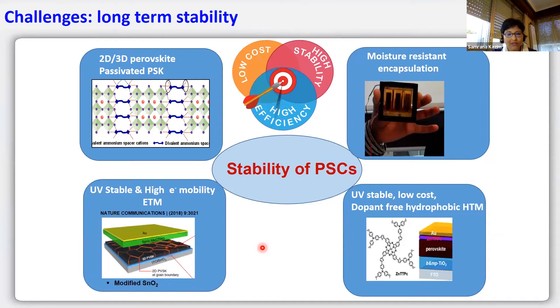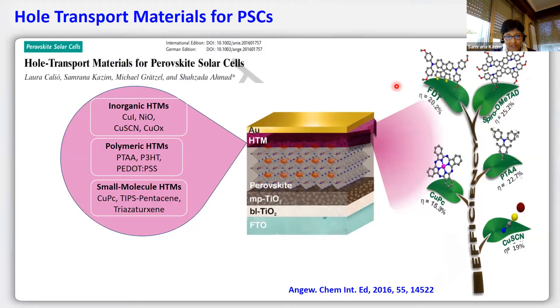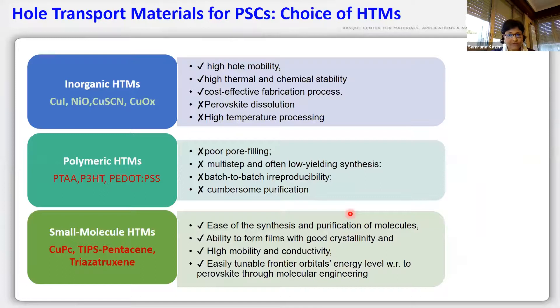We have been working in this direction since 2012 and have been making several different types of hole transport materials — some can be used without dopant and some require dopants. Different types of hole transport materials can be used: pure inorganic p-type semiconductors such as copper iodide or nickel oxide, organic p-type semiconductors divided into polymers such as P3HT, PTAA, or PEDOT, and small molecules such as triazatruxene, triazine, or pentacene, as well as organic molecular complexes like phthalocyanine. Organic p-type semiconductor-based HTMs have always been the front-runner for improving efficiency.